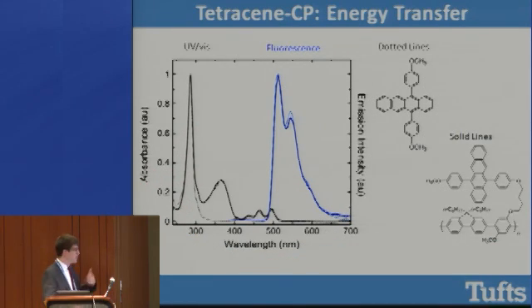Okay, so what does the polymer do in comparison to the furan derivatives I showed you before? Well, what I'm showing you here are, in dichloromethane, again a halogenated organic solvent, the optical properties of this acene here in dotted lines. And so you can see that for this acene, we see the characteristic signals for a tetracene. That is, we see this very sharp signal in the UV and this characteristic vibronic pattern in the visible region of the spectrum. And we also see a very sharp and well-behaved fluorescence spectrum in the green region of the spectrum.